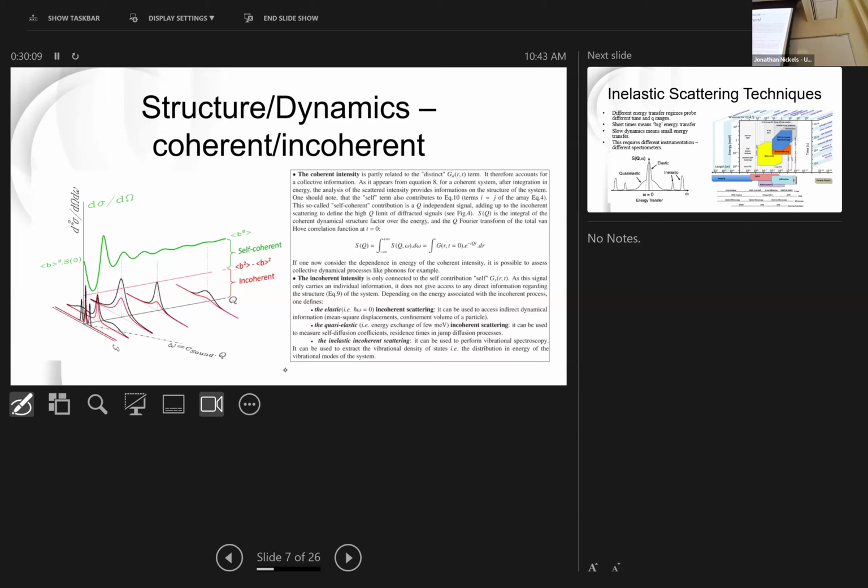As you go to shorter length scales, these incoherent broadenings in your peak are going to tell you about different types of motion in your system. So it might be backbone relaxations, right? Slow. You start slow. So maybe you have incoherent scattering coming from the relaxation of the polymer backbone. Or you have relaxations in the side chains. Or maybe you have a co-solvent in there to keep things plasticized, and you see the diffusion of the solvent.